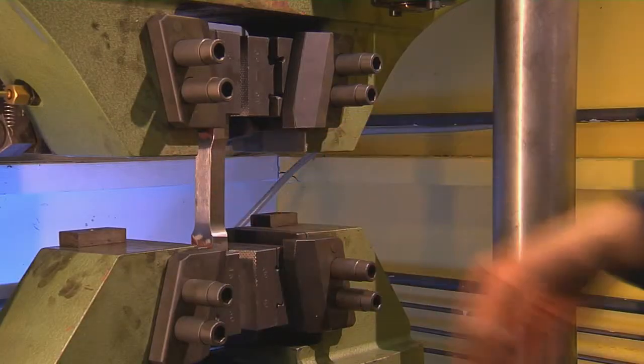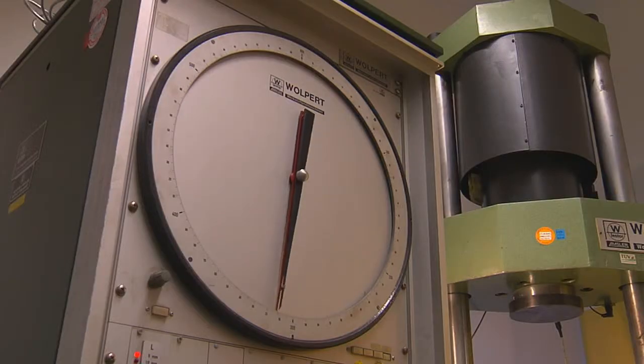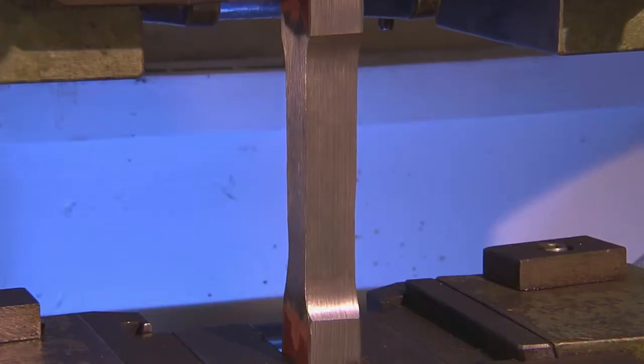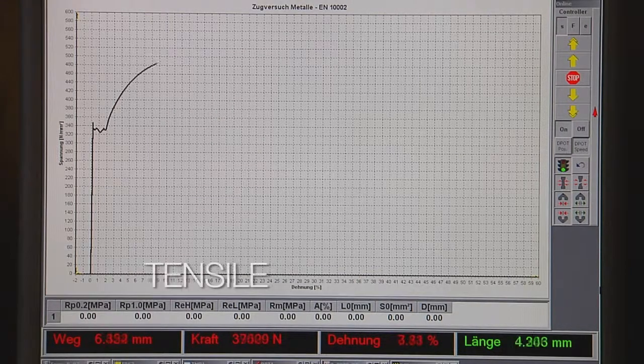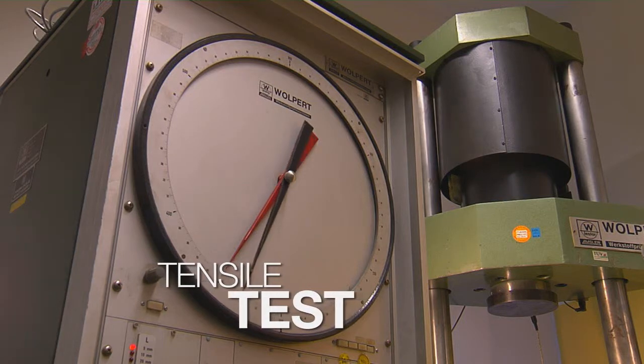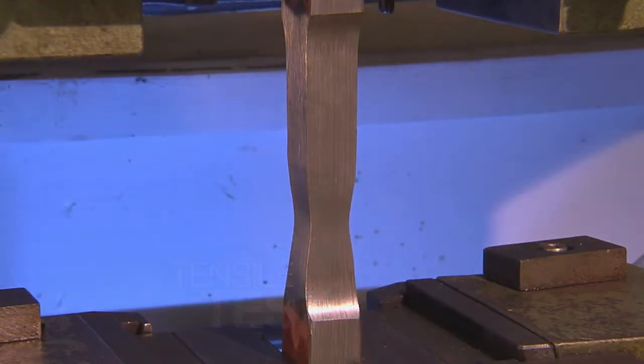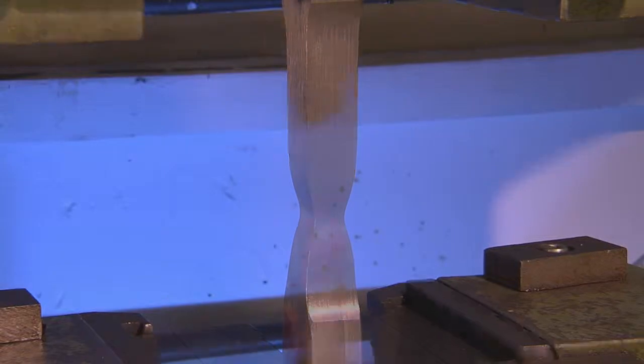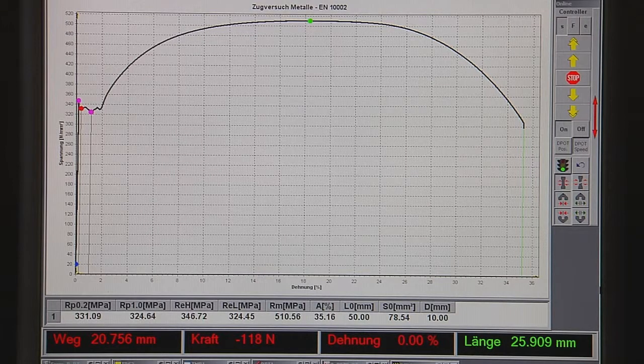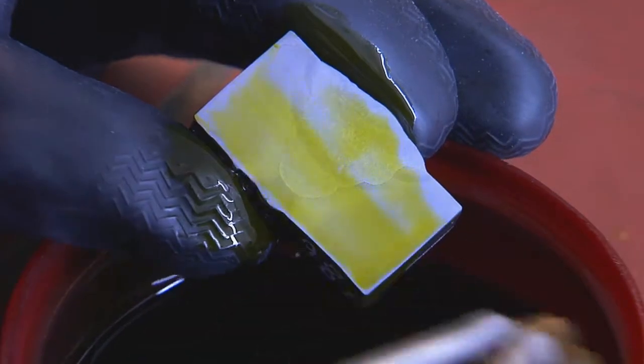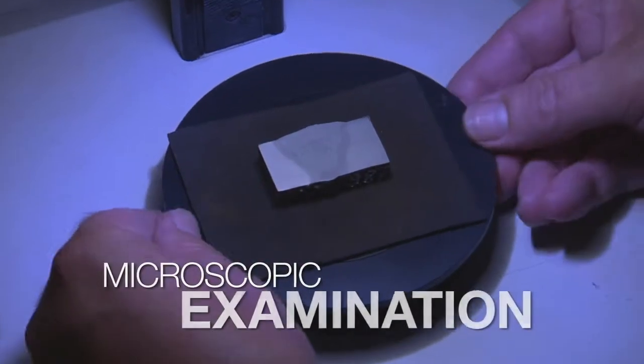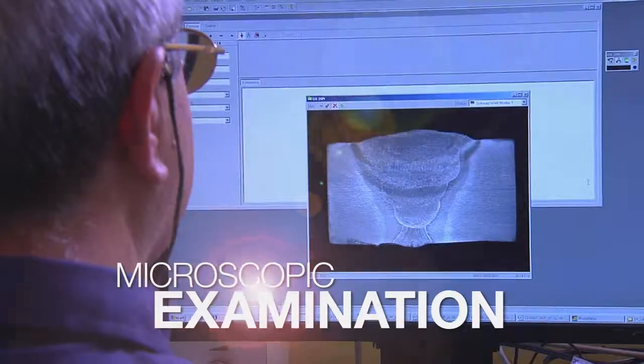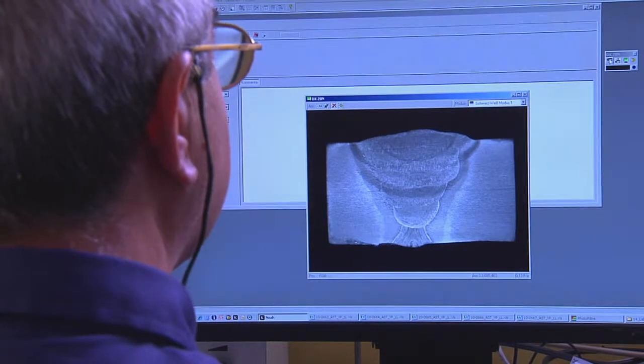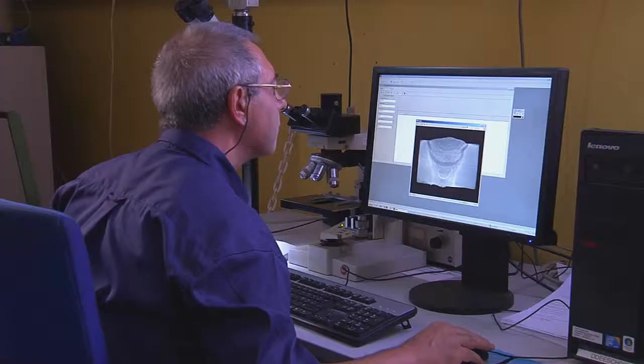All these tests focus on the key mechanical technological figures for the weld seams. The tensile test shows the forces at which elastic deformation ends and plastic deformation begins, until finally the base material tears. The weld seam holds. The macro section constitutes the preparation for examining the sample under a microscope. The enlargement on the monitor clearly shows the base material, the filler, and between each of these, the heat influence zone.